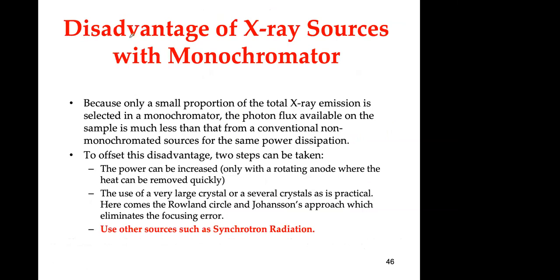So what is the disadvantage of using a monochromator? Well, for sure you're going to have fewer photons hitting your sample. So the flux of photons will be lower because you're basically filtering the X-ray source. Not all the X-rays generated in the anode are going to reach your sample. So that's a disadvantage. To improve that, you can do a couple of things: increase the power, which will make the lifetime of your source lower.